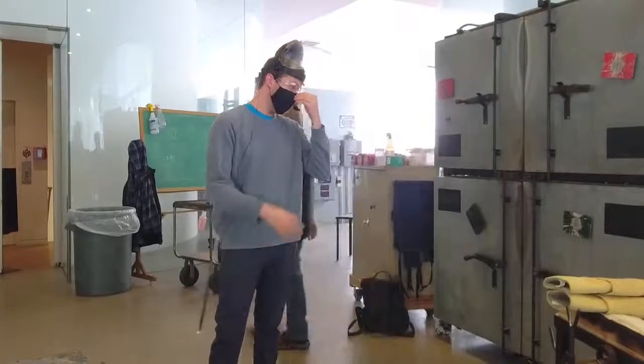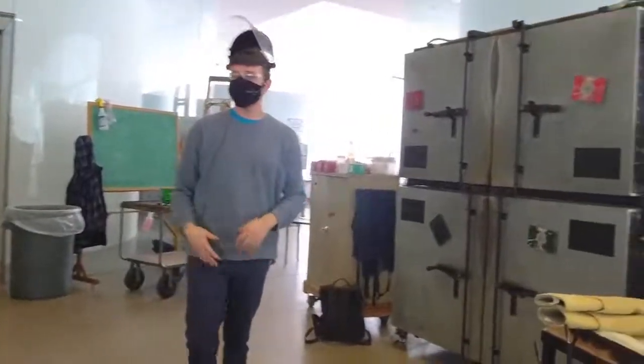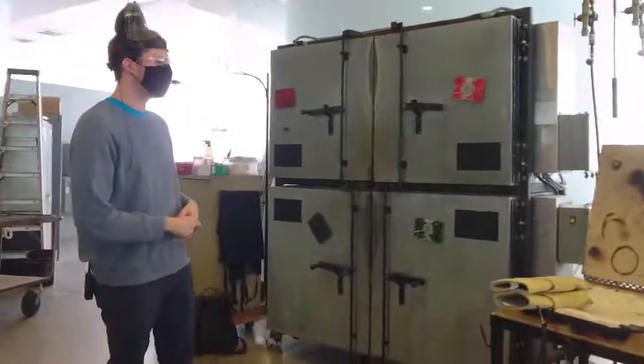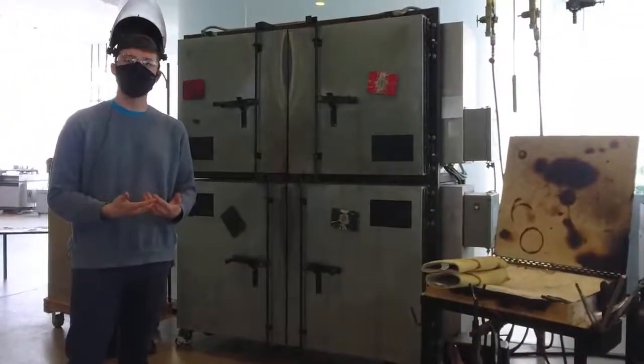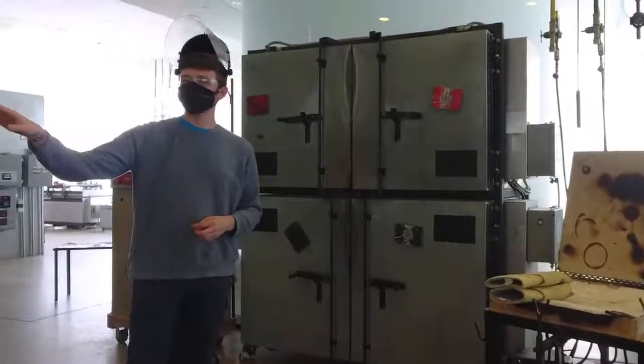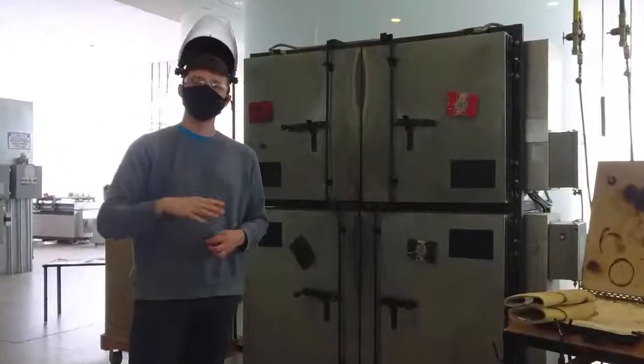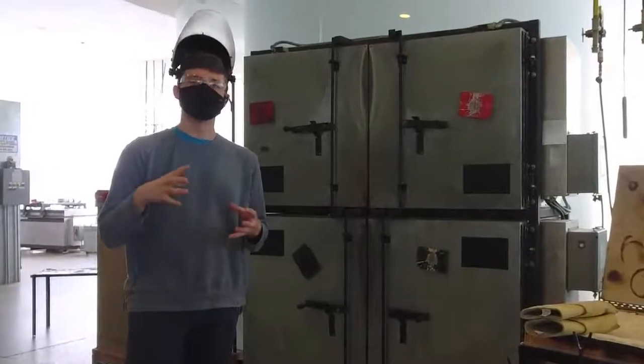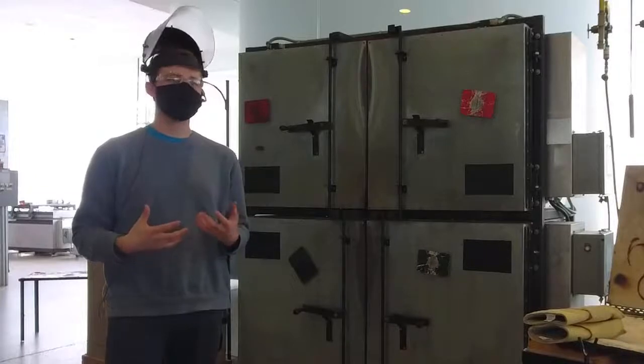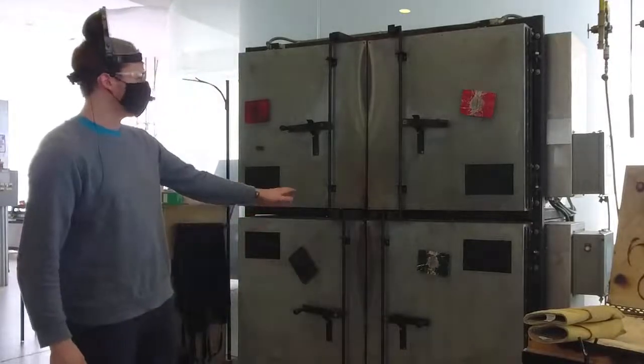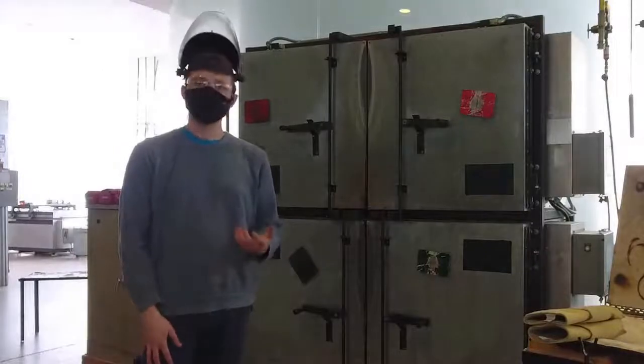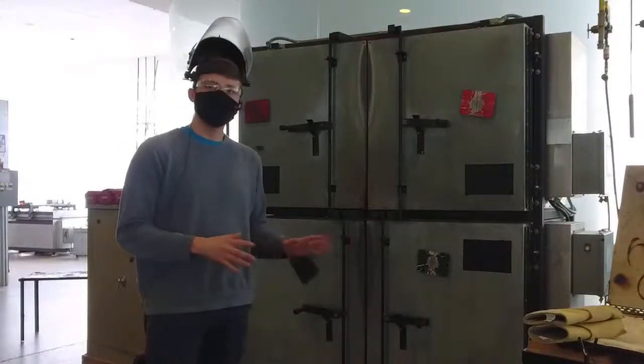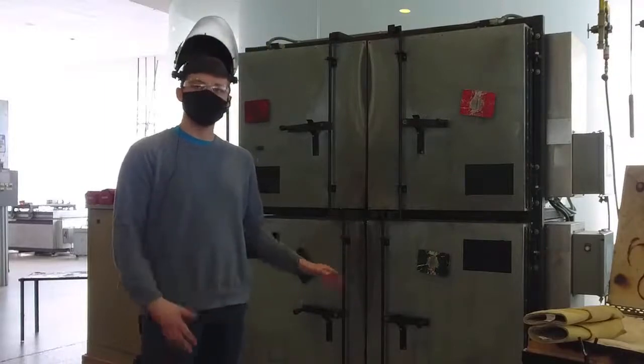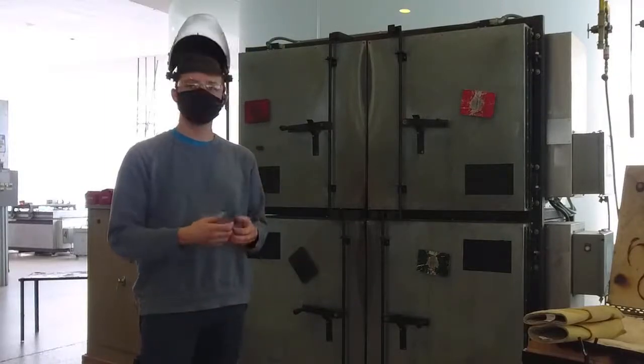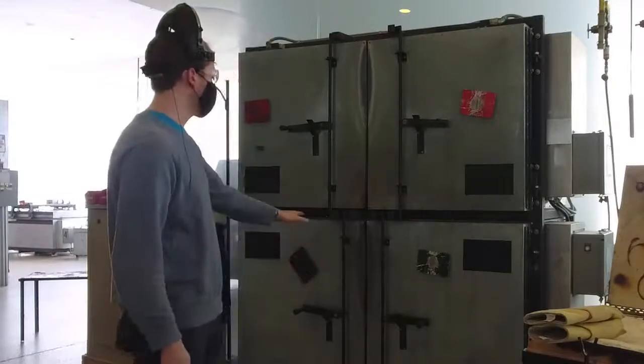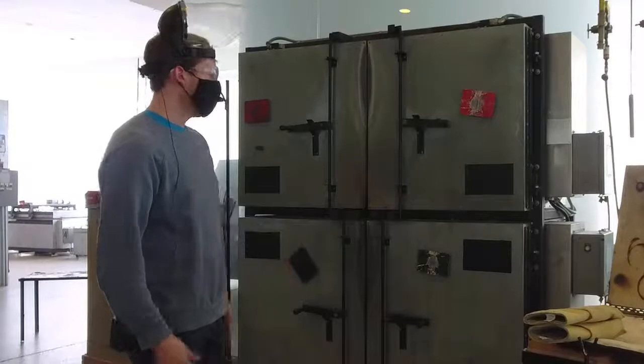Because the glass that we're using in our studio is a soda lime glass, that means it is a soft glass. So essentially what that means is it is very susceptible to thermal shock. So all of the flashing that Colin was doing to the piece right before we removed it is to even out the temperature and get it to a nice and stable, roughly 1,000 degrees to 950, because this piece of equipment here is holding at 918 degrees, and that's a very, very stable temperature for our glass to rest at. And at that temperature, it's not hot enough to slump, and it's not cold enough to induce thermal shock. So the piece can rest in here inside of our annealing oven as long as needed.